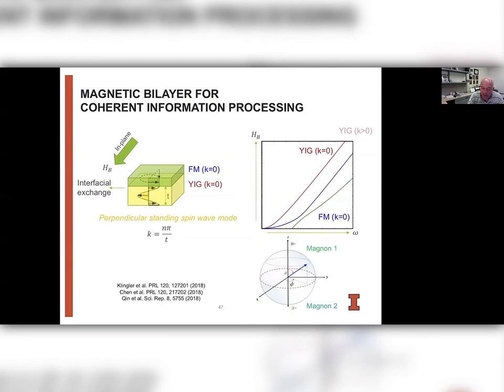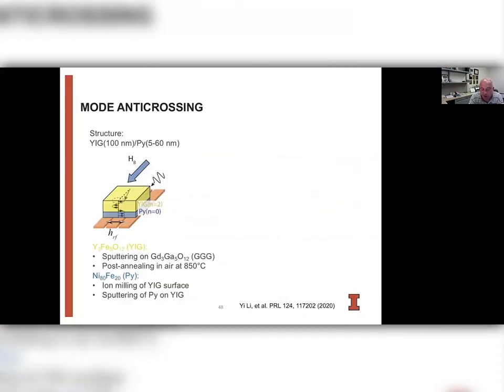So this then is what motivated our experiments, where we use yttrium iron garnet films that are fairly thin, of 100 nanometers, which is about an order of magnitude thinner than what was earlier used with the cobalt layers. And in order to have a similar magnetization, we use then permalloy layers that have a significantly lower thickness, with varying thicknesses. So we grow the yttrium iron garnet on gadolinium gallium garnet.